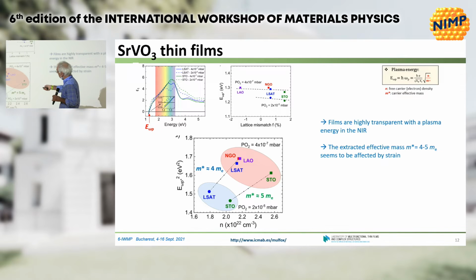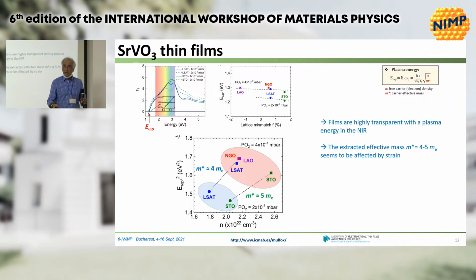And better, you see this plot. Here is this energy as a function of the number of electrons measured by Hall effect on samples grown on different substrates. This plot shows that the plasma frequency depends on the substrate you have used, LSAT or LAO or STO. But more important than that, it shows that for a given concentration, the plasma frequency is different. See, for a given concentration, let's say 2.0 times 10 to the 22, in films grown on STO, we will have one plasma frequency, and on NGO and LAO, we have another plasma frequency.